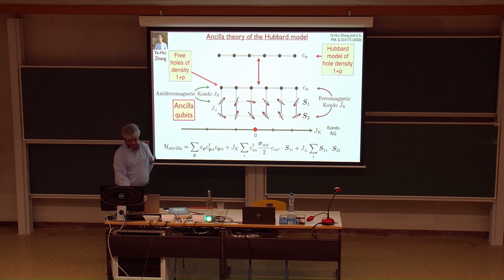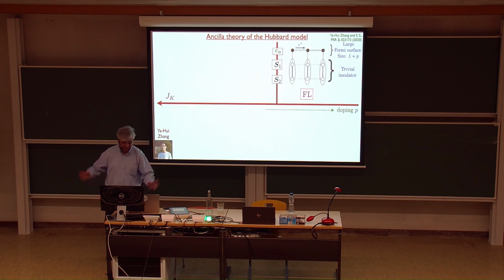And this is the RG flow for a single spin Kondo effect. If it's positive, it flows to infinity. If it's negative, it flows to 0. There's a fixed point at JK equals 0. And so we assume we're here and it's going off to infinity. So it could happen that under the right circumstances, at long distances, we should really think of JK becoming bigger than J perp. Microscopically, it's not, but when I do the many body physics and include the Kondo RG, that's a reasonable possibility. So that's really, in the end, the only unproven assumption. Once you make that assumption, I'll show you, you get exactly what you want.